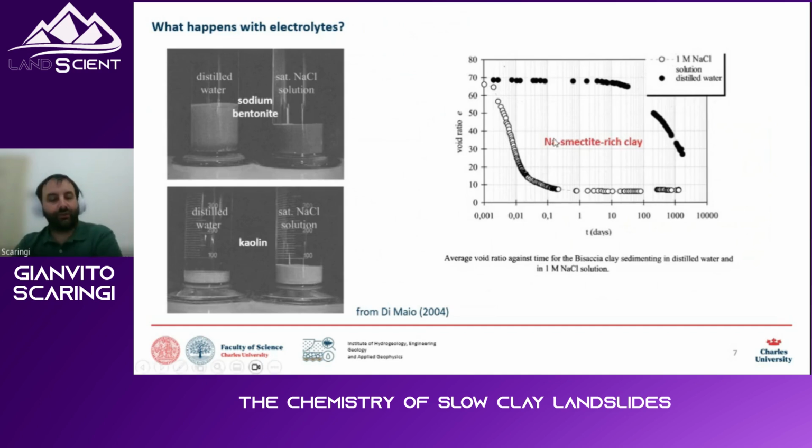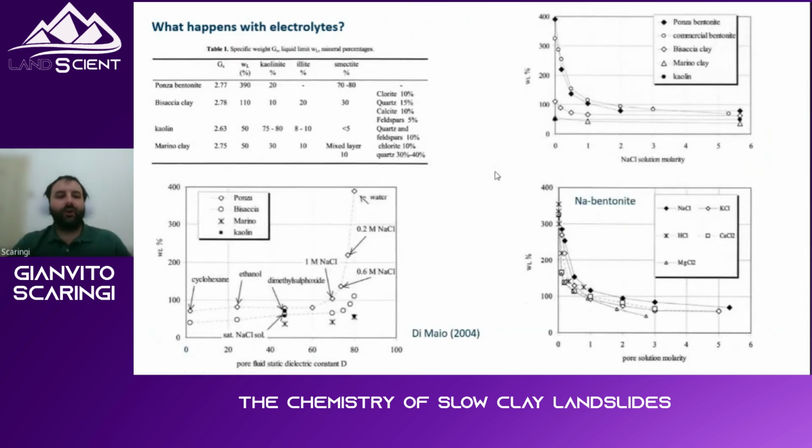But if you have a salt solution, so the same clay in seawater, or if you add salt to the water, it's going to flocculate and settle within minutes, maybe 1 hour or 2 maximum. So the sedimentation, because the particles flocculate, in fact, they get bulky, and so they precipitate. Basically, you have a precipitation of the clay. Very, very interesting. But if you move farther from the sedimentation, so it's where the clay is actually formed, to the basic properties, you will also see, now that the slide comes up, that